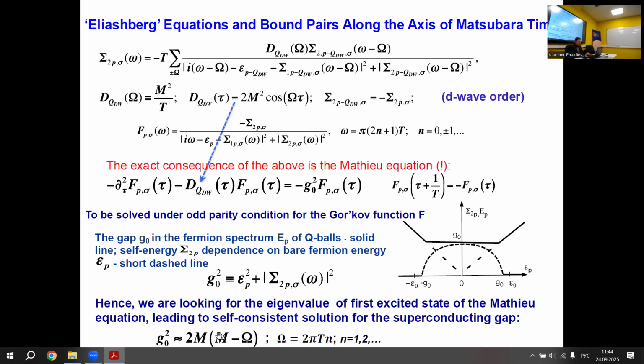Well, this is very important because you see that this solution appears only when the amplitude m becomes greater than omega. It means that the Cooper pairing would be a first order phase transition with respect to the amplitude m of the Q ball. So you cannot get a Q ball of arbitrarily small amplitude, because then you have no solution of the Mathieu equation for the first excited state. This is well known: in a very shallow one-dimensional potential well, the lowest level always exists, but the second level only comes when the depth of the well has a finite value. This is a manifestation of a well known fact from elementary quantum mechanics.